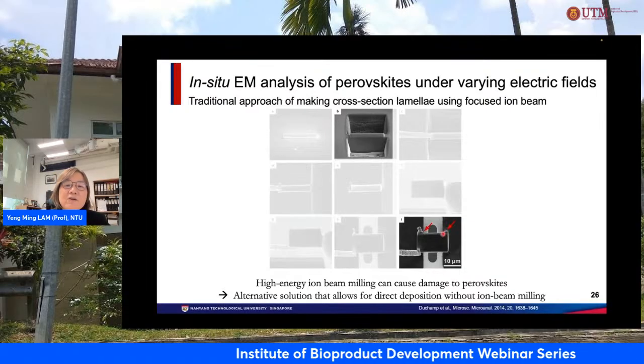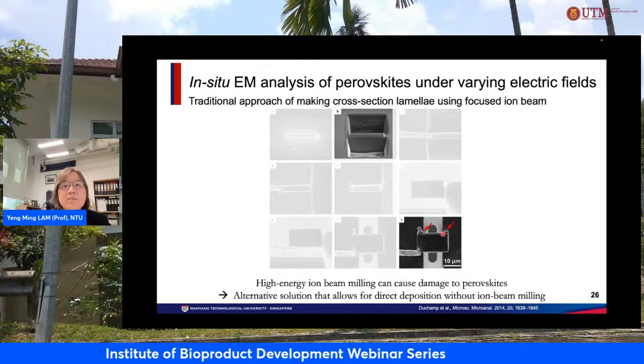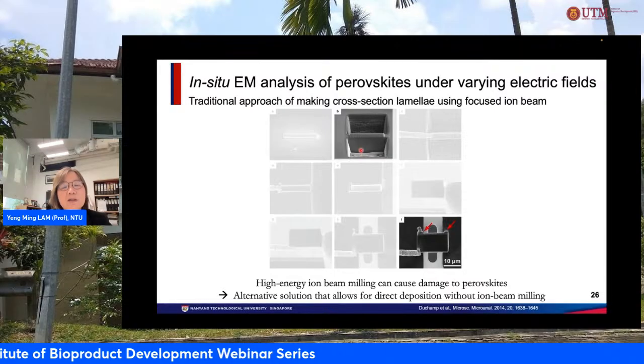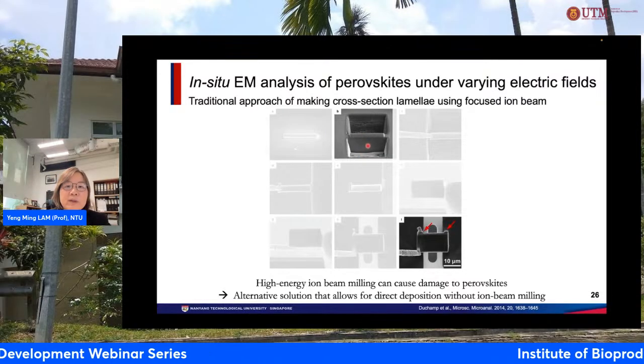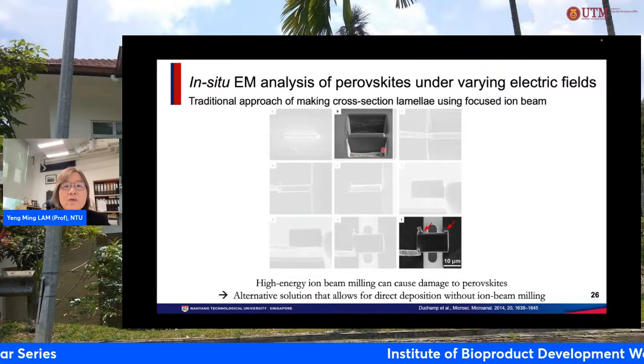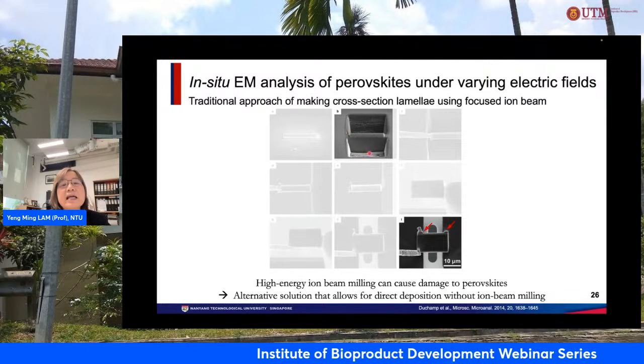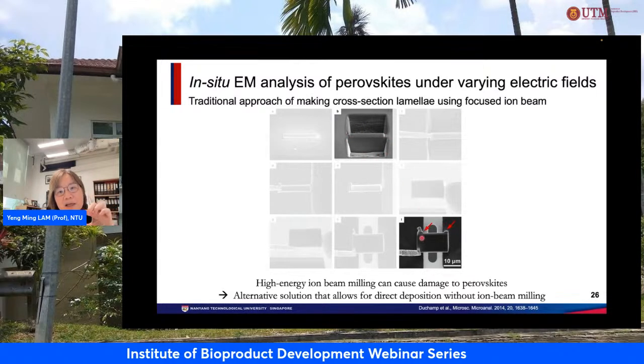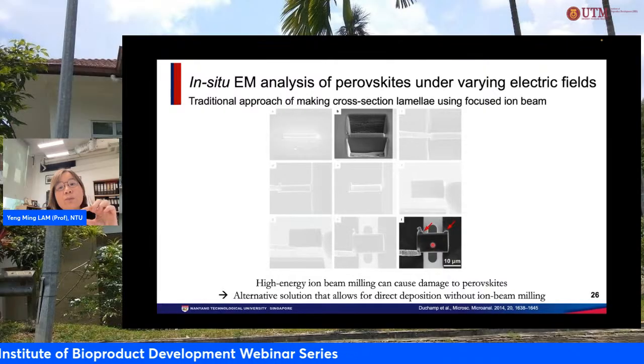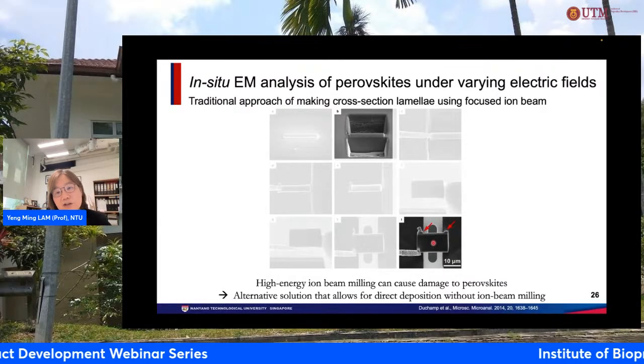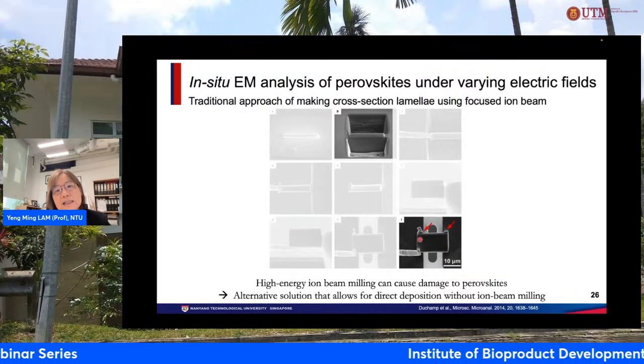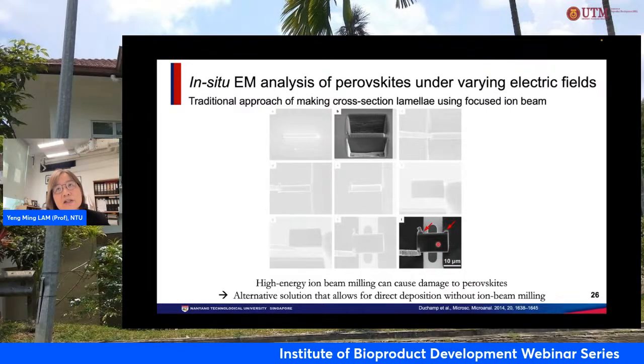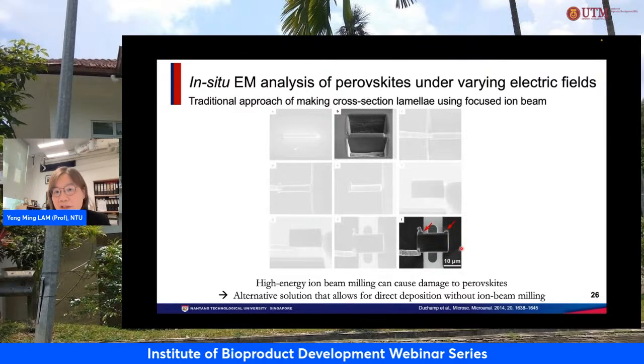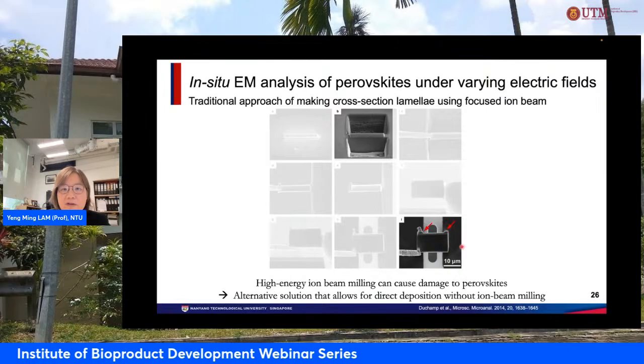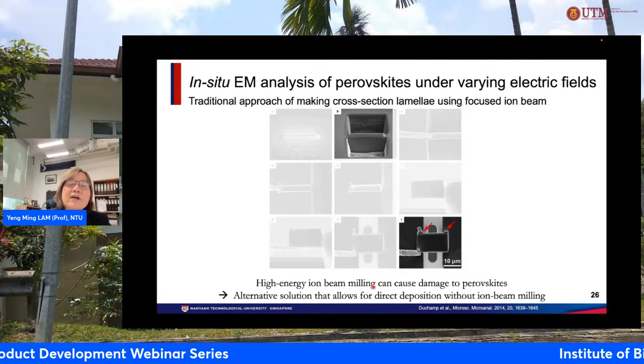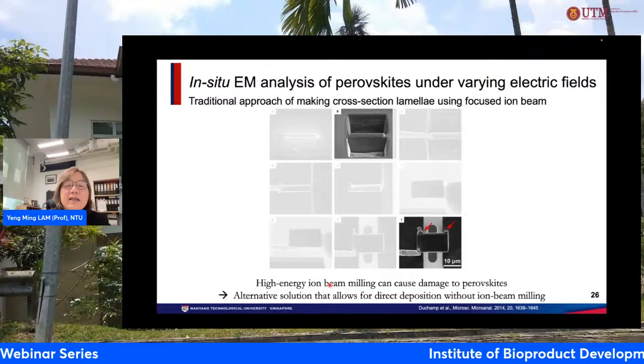So generally, if you want to study this material, so this is now talking about characterization, most of the time, people will use focused ion beam. This is the way that focused ion beam works. It etches away the material on both sides, and then this thin slice of sample is picked up eventually to be investigated under the transmission electron microscope. This thin slice of material has to be less than 100 nanometers in thickness. It's very, very thin.